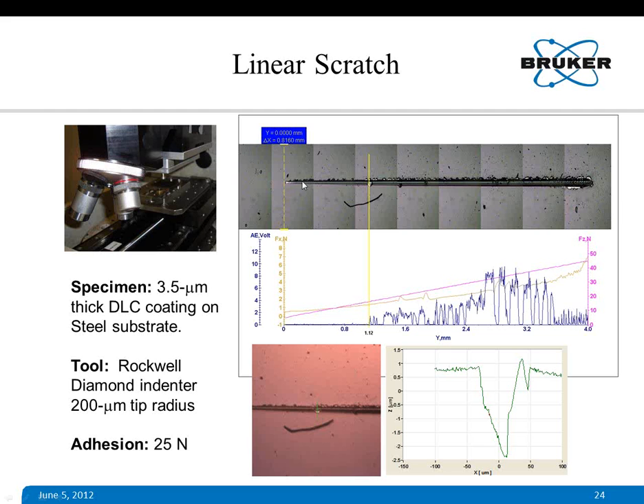You can see some of the chipping started, but the interesting thing is that at this point it actually first delaminates the coating, that is, the coating is completely failed here. And you see there is not much indication of change in lateral force, that is Fx, but there is an indication from acoustic emission. It started showing some events from the point of failure onwards, which indicates that actual failure occurs here.